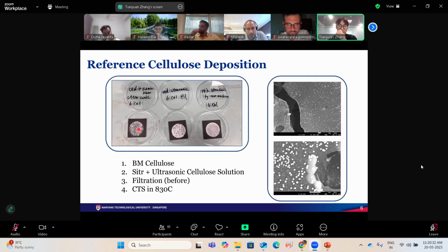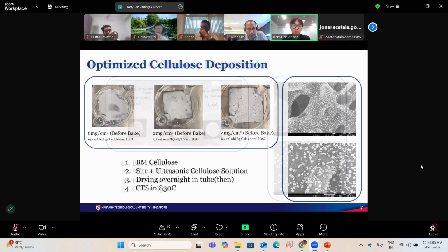And we suggest that it's mainly because the bottom is vacuum and there is a force that makes some cellulose drop down, and the cellulose will be lost, and the coverage and uniformity turn very bad. So cellulose is a big problem. It is very hard to make a thin, uniform, and high coverage cellulose layer with this original cellulose deposition method. And after this, we optimized the cellulose deposition method.